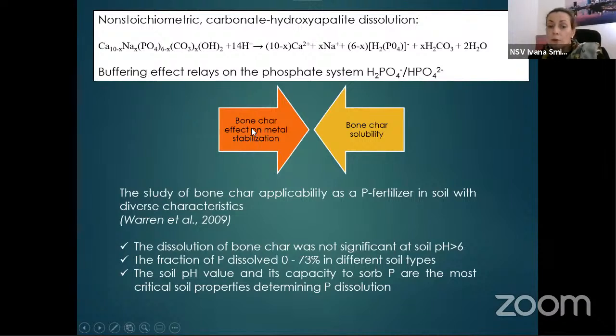It is known that the bone char effect on metal stabilization is closely related to the bone char solubility in the soil. This reaction globally presents the dissolution of one carbonate-substituted calcium phosphate in the presence of the acidic medium. This reaction also explains the buffering effects of the hydroxyapatite, which relies on the phosphate system.